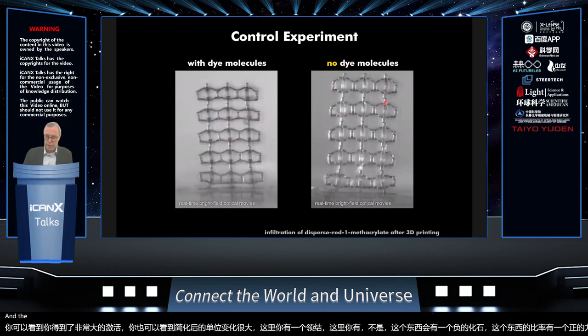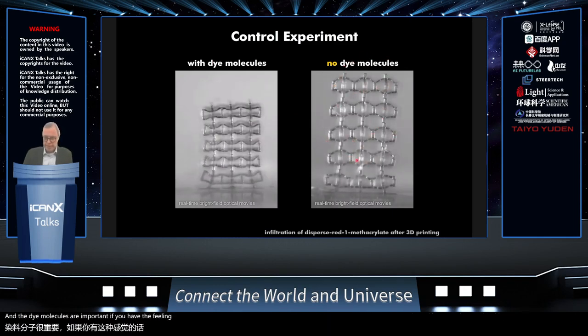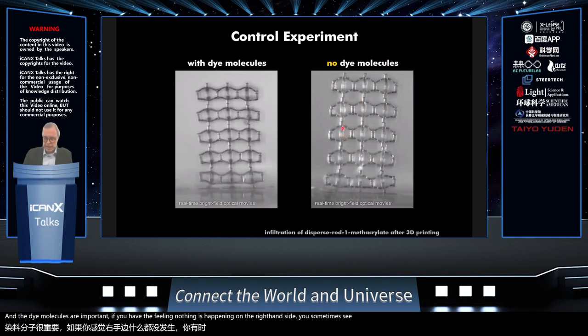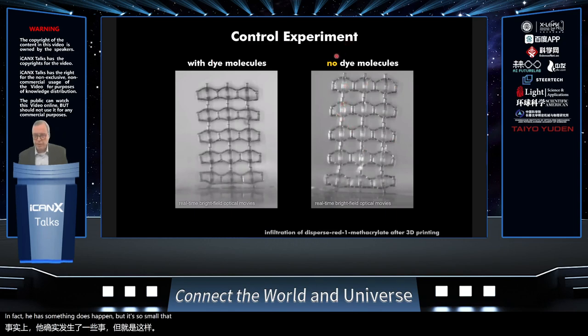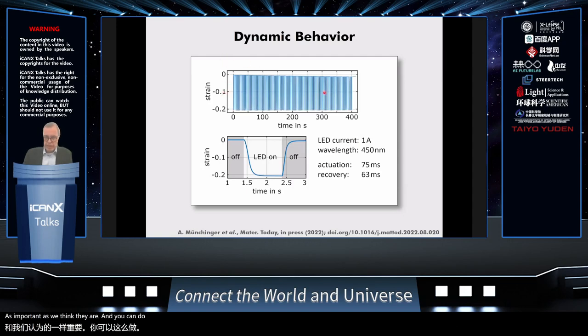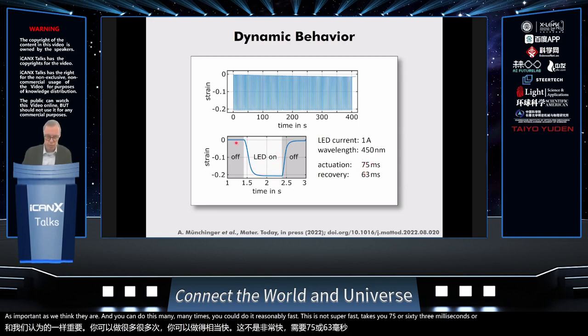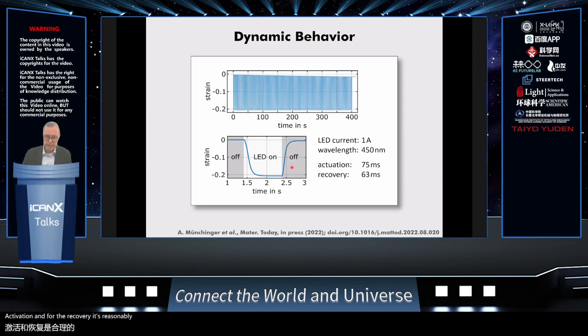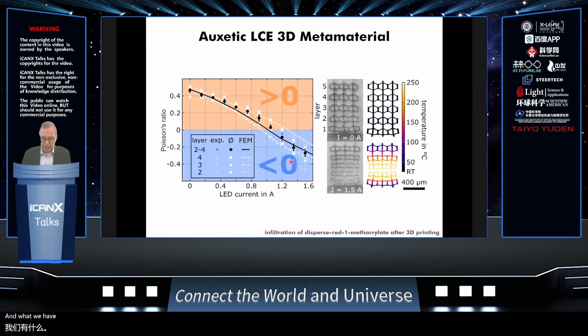And the dye molecules are important. If you have the feeling nothing is happening on the right-hand side, you sometimes see the light level changing a little bit. In fact, here something does happen, but it's so small that you cannot see it. This is just our control experiment that the dye molecules are actually as important as we think they are. And you can do this many, many times. You can do it reasonably fast. This is not super fast, takes you 75 or 63 milliseconds or so for the actuation and for the recovery. It's reasonably fast.